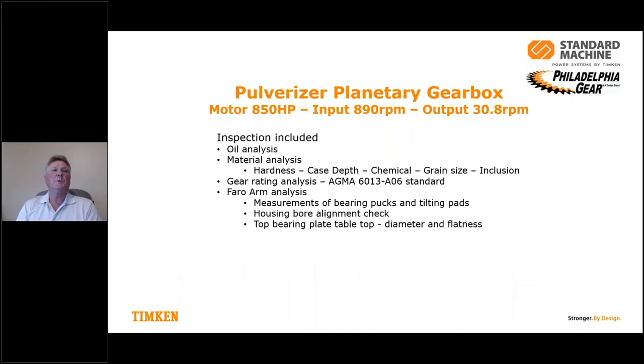We did a complete oil analysis, and we did a deep dive into the material. We looked at the hardness, the case depth, the chemical composition, the grain size, and the inclusions, if there were any. We did a complete rating analysis using AGMA 6013-A06 to determine what this gear should be rated at, the ring gear and planet gear.